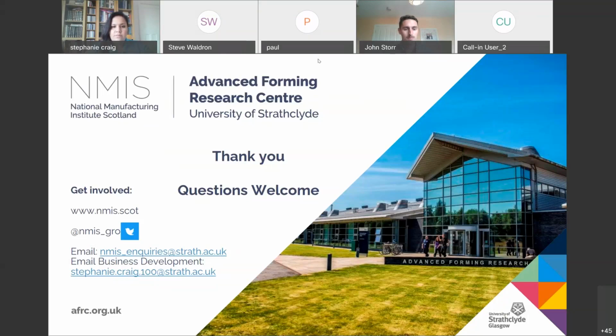With the titanium part, as I mentioned in my preamble, you would normally need to take the part and remove some alpha case off it, so you need to allow for that. With aluminium, no issues there really. Aluminium doesn't really suffer from the same problem. So in terms of the accuracy of the process, pretty tight. Obviously you've got to be able to get the part out of the press, so you'll need a certain amount of radius on the sharp edges, but other than that, a fairly accurate forming process, and that's really one of its big selling points. The fact that the material is superplastic means that you can form fine detail, which is one of the big value adds of this type of process.